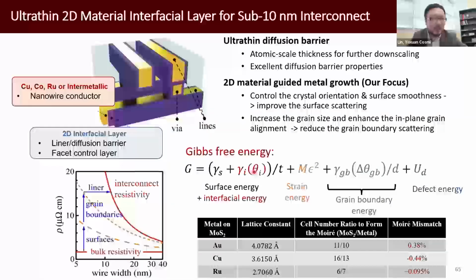And if there is a good lattice match, we can also mitigate the strain energy. And if we consider when the crystals are aligned, we start with nucleating and depositing individual domains. And when they start to merge, we also need to consider grain boundaries. And if the domains are more or less aligned, the grain boundary energy can also be reduced.